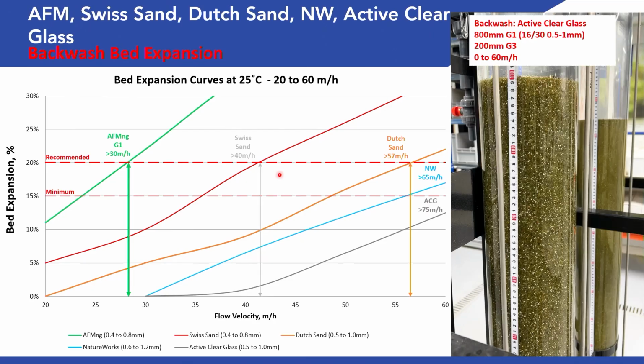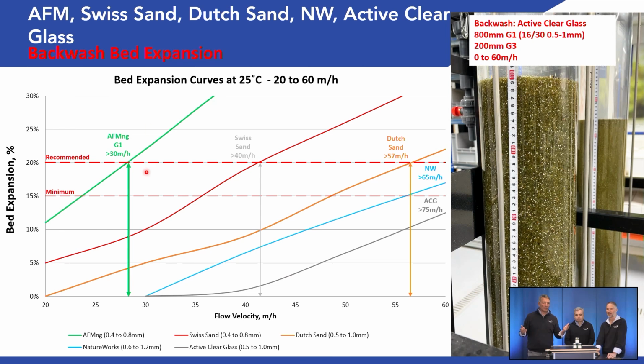Sorry to say. But coming back, we have with AFM, we have 30. Swiss sand, which is also German sand, the best quality sand we ever tested. You're just above 40 meters that you need. Yep. Same grain size, by the way. Same grain size, 0.4, exactly. 0.8. It's just because quartz sand is slightly more heavy. It's higher density than Dutch sands from the Netherlands, 57. Okay, slightly bigger is 0.5 to 1, but you see what big impact this has, and probably also the shape.